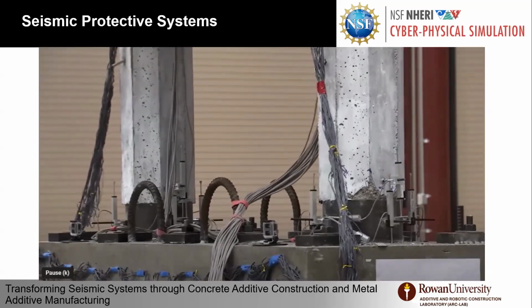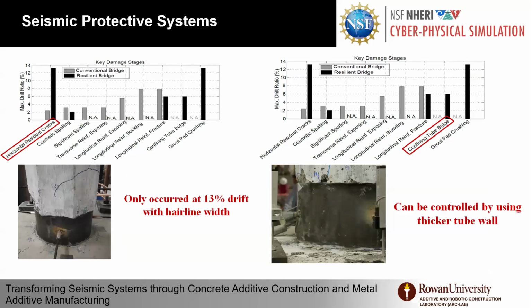We faced a lot of challenges in the aftermath of this testing because a lot of ruptures happened in the rebar that we were not able to inspect because everything's recentered off nicely. However, as you can see here, the tubes are actually preventing the visual inspection too. So, as you can see here, the only crack that happened to the column was at 13 percent drift ratio.